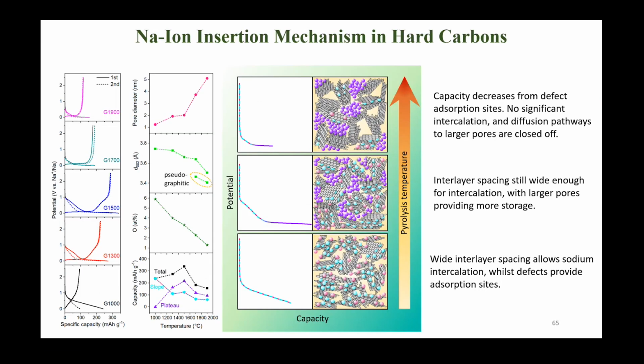And just to tell you, the conclusion is that you want to be in this situation here, where basically if you have very big disorder, sodium randomly adsorbs on the carbon, but you'll have very poor irreversible capacity. Now, the ideal case is where you have some pores, and in this plateau, sodium goes and sits in the pores. But in order for sodium to go to these pores, you need to have the right interlayer spacing so the sodium penetrates to this pore.